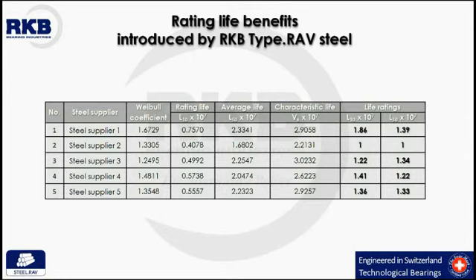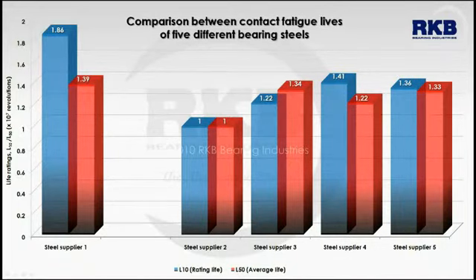The material samples were annealed and manufactured into washer samples, hardened in a gas-protected electro-furnace between 835 and 845 centigrades for 50 minutes, and finally tempered between 150 and 160 centigrades for 3 hours. The evaluation was performed in a life prediction tester with a maximum contact stress of 4,508 megapascals and 2,040 revolutions per minute. The results were as expected.